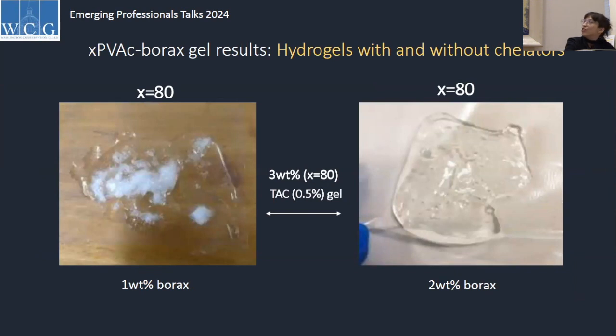So this is quite a contrast. Essentially, these systems are very sensitive to salt solutions, so that also includes the sodium in the borax crosslinker. So you don't want to put too much borax solution in the gel. And you will get a syneresis effect, so it'll phase separate, or it just won't gel properly, or it'll disassociate and have issues. We worked with the recommended parameters in the literature for 0.5% chelating solution, and that's really the acceptable amount that you can get into these systems before you have issues.